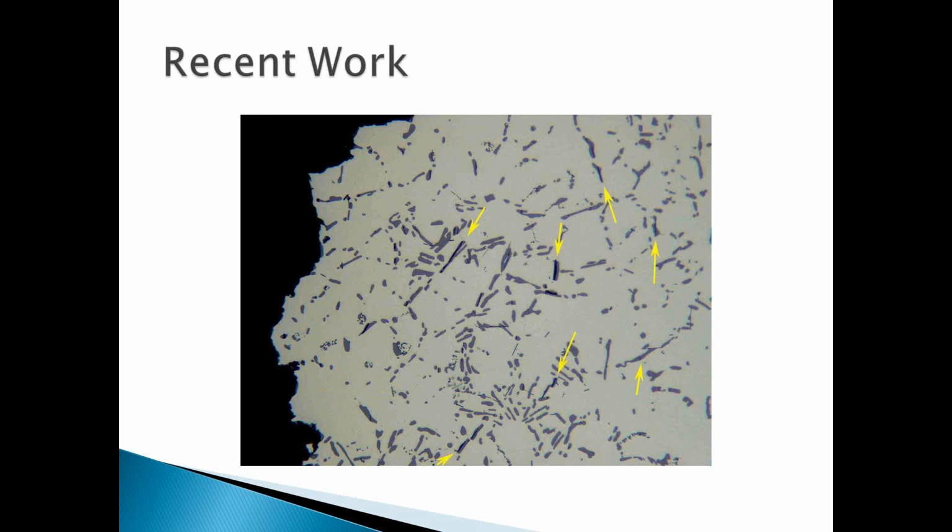But when you go and you produce very, very clean aluminum that are free of oxide films, there's a ceiling to the mechanical properties that you can get, because what happens is the material begins to fracture at the silicon that's added to the alloy.